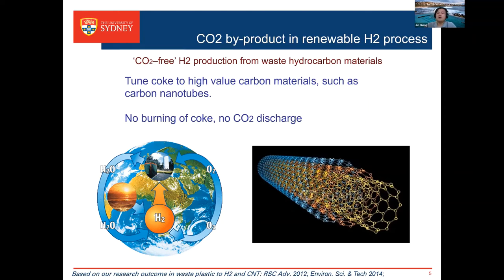But there's another issue. How about the carbon? The carbon will transfer to coke. This is a waste material, and normally if we burn the coke, we will generate a large amount of CO2. So this is not our target. In this case, we are thinking about whether it is possible to design a catalyst, this magic material, to generate the hydrogen and at the same time convert coke, this waste, to carbon nanotubes or carbon nanofibers. This kind of useful carbon material has a very big market globally. Therefore, we are able to avoid the burning of the coke, and then no CO2 is discharged when we transfer waste plastic to energy and fuels.